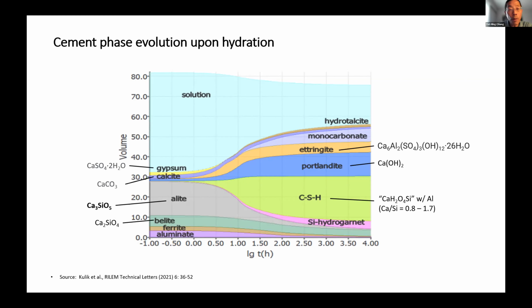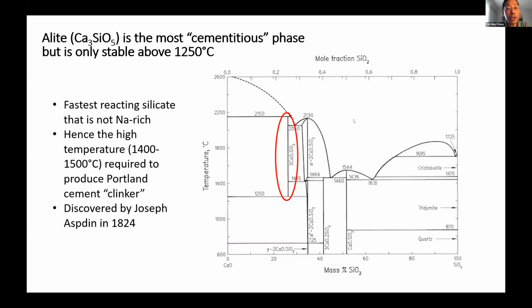So an interesting part of this compound alite, tricalcium silicate, is that if we look at the calcium silica phase diagram, the red circle here is the alite phase, tricalcium silicate. And what you notice is that, well, there's a eutectoid here. It turns out that that phase is only stable above 1250 degrees C. Right? This is the reason that Portland cement production today is a high temperature process. It was discovered in 1824 that this tricalcium silicate is the fast reacting silicate, excluding sodium silicates.